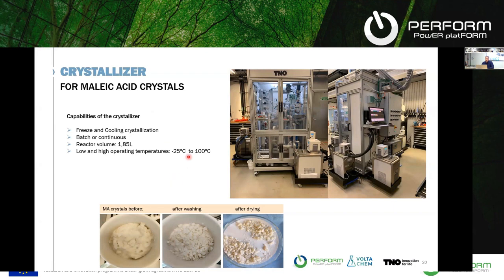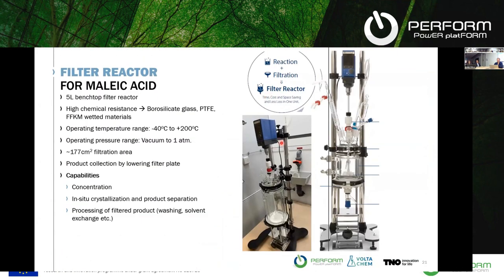As I said, after the concentration step, we have a crystallization step to get maleic acid crystals. We developed this entire setup to carry out this crystallization, and we even did a test run. And here are the pictures of the maleic acid that we get out. One drawback of this setup is that the actual volume that we can use is a bit limited, and we also have a bit of material incompatibilities in the setup. So this is why we went for a different solution very recently.